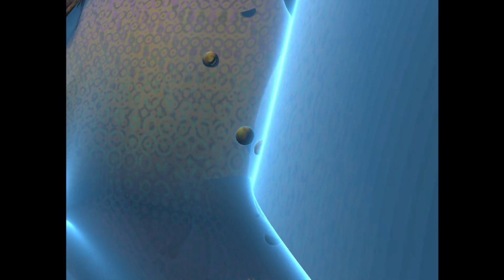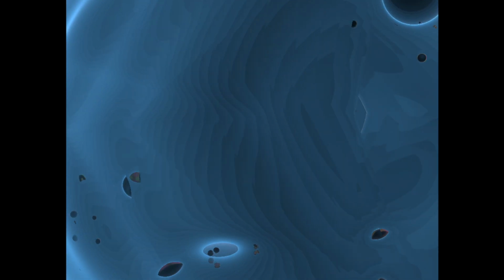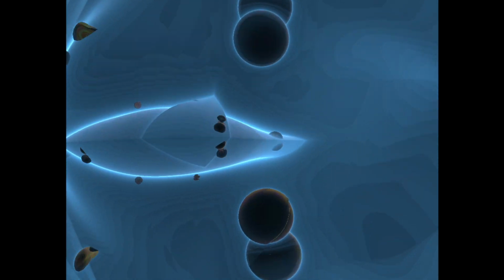And what are the characteristics of a Hund's metal? Well, you often get strong magnetic fluctuations coexisting with charge carriers that are still somewhat mobile, but not perfectly well-behaved. This helps explain the bad metal behavior seen in the normal state of many FeSCs. Bad metal, meaning high electrical resistance, poor conductivity. High resistivity, often with a strange temperature dependence, and the quasi-particles, the effective electron-like excitations, lose their sharpness. They become less coherent, less particle-like.